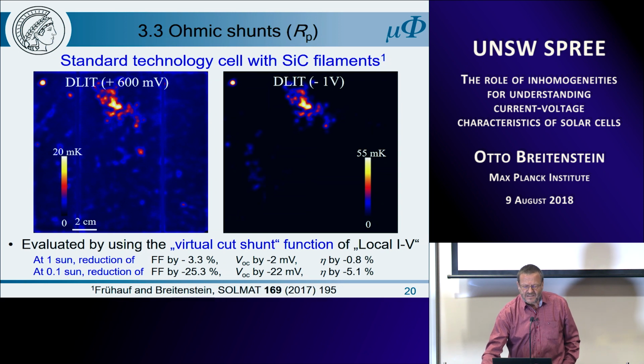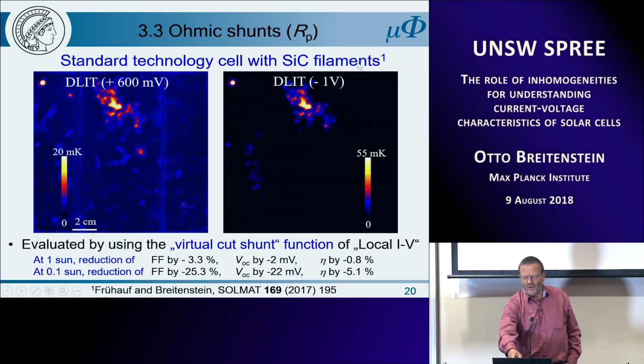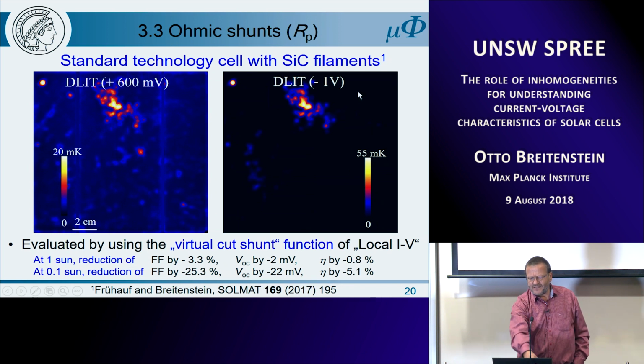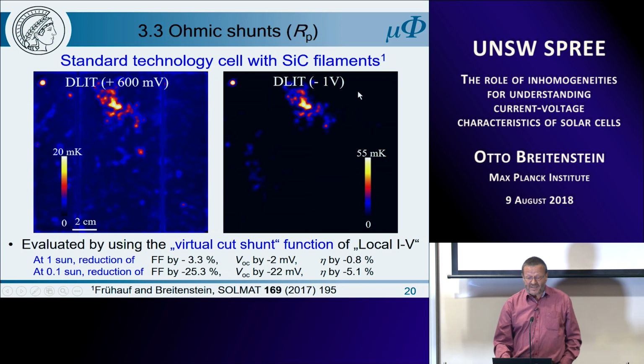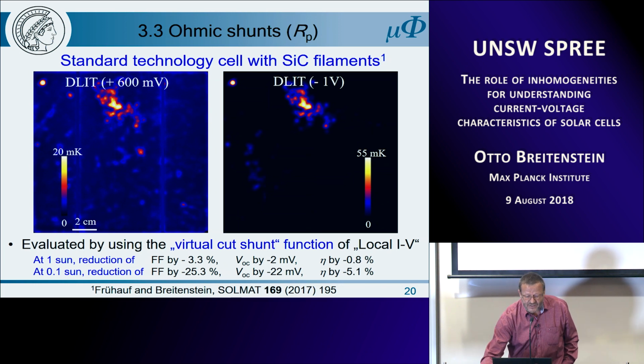And this is a lock-in image at plus 600 millivolt. That's high enough to show also the J01 and J02 current. And at minus 1 volt, it looks like this. And so all defects which appear in both images are the ohmic shunts. And so one by one, I have cut them out.